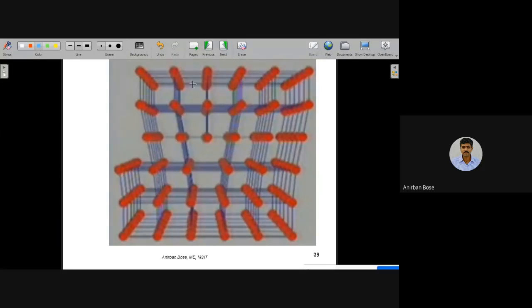So if you see this particular plane, you observe this is a particular plane actually. If you go in the other direction, this is basically the plane, you can understand, and along that plane basically the atoms are there, as you can see. Okay, so if you observe this particular plane, this plane is not a complete plane, this is a part plane, because the other part is not there. There is no continuation of the plane, that means the atoms are missing, so that plane is not there. So this is a half plane, or not a complete plane.